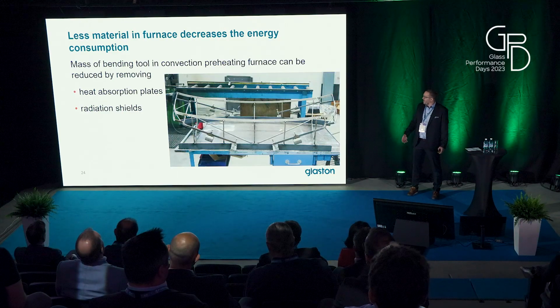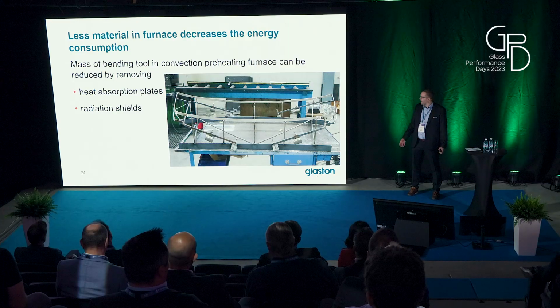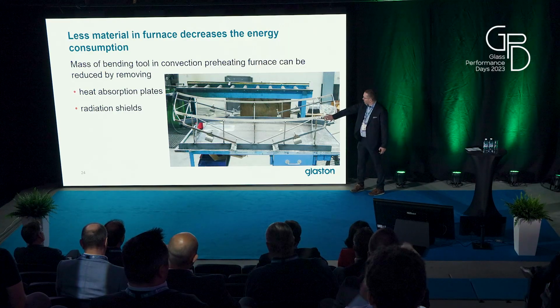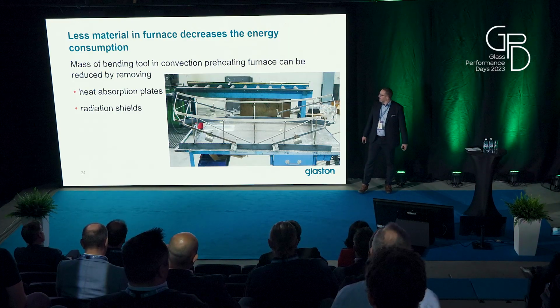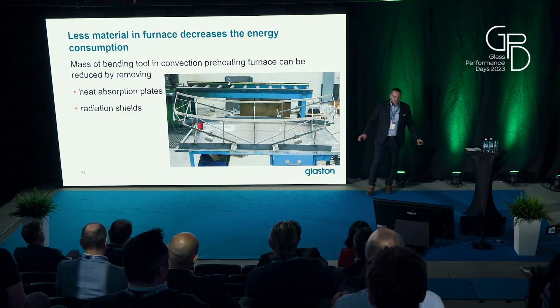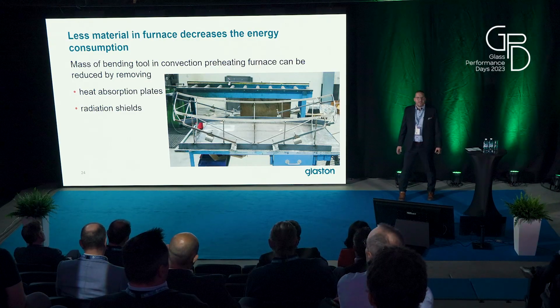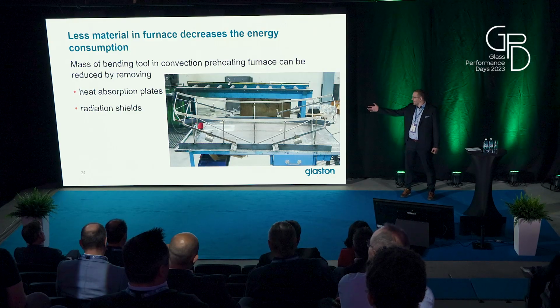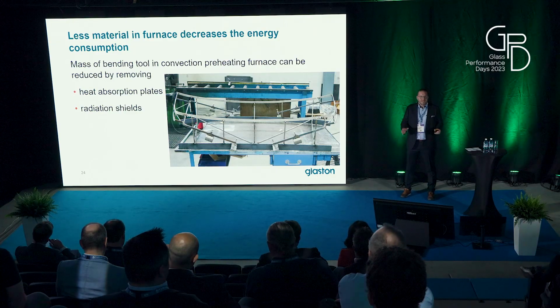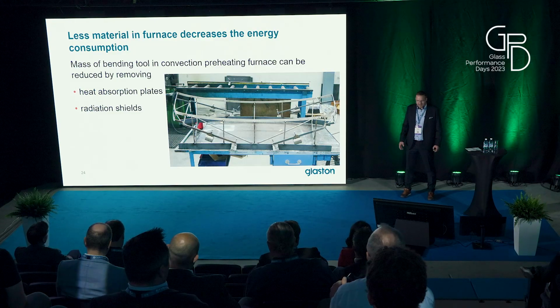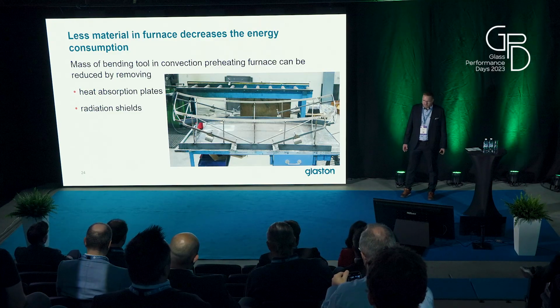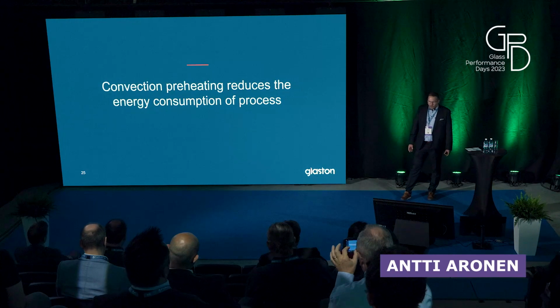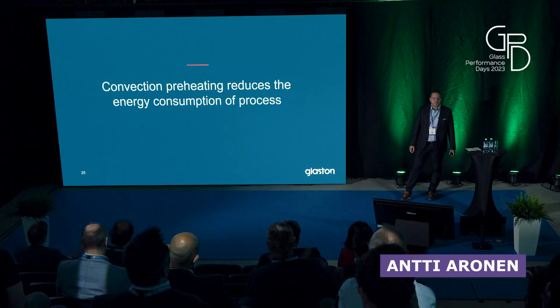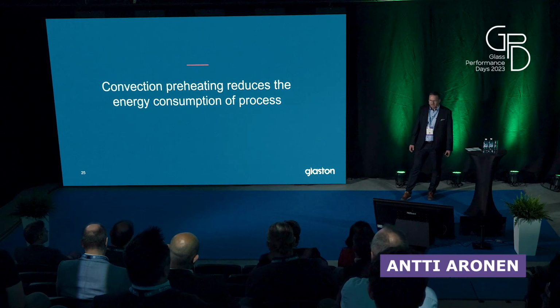So by adding convection, we can use a much simpler construction for this bending tool, and we don't have to use so much energy for heating just the bending tool, because the main target is to heat only the glass, but the bending tool is coming in the way. So we can reduce energy consumption also with this convection preheating.